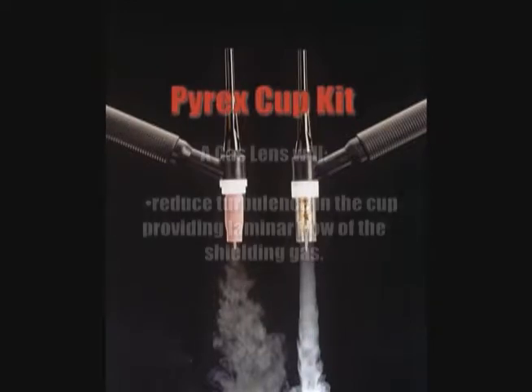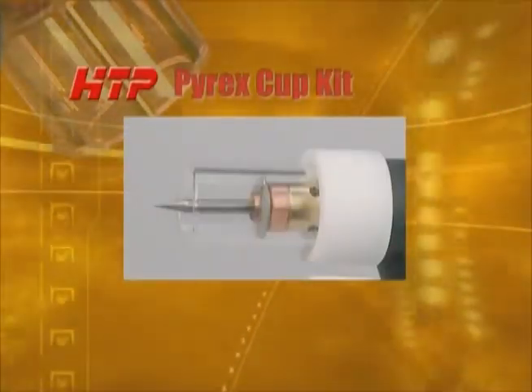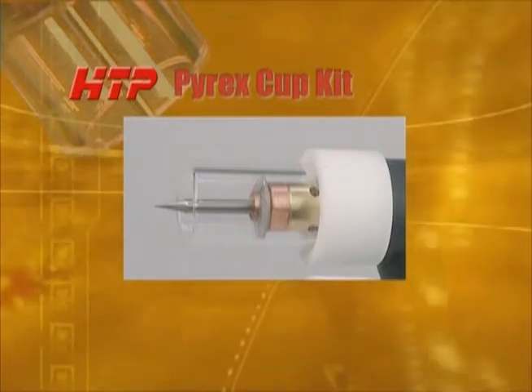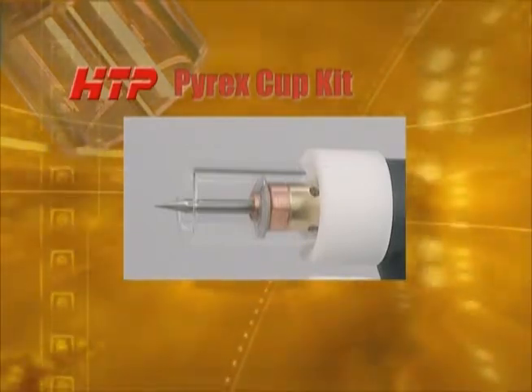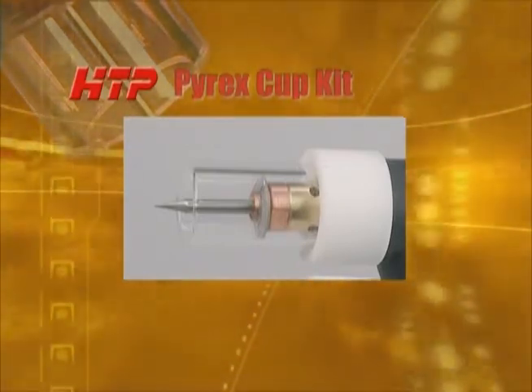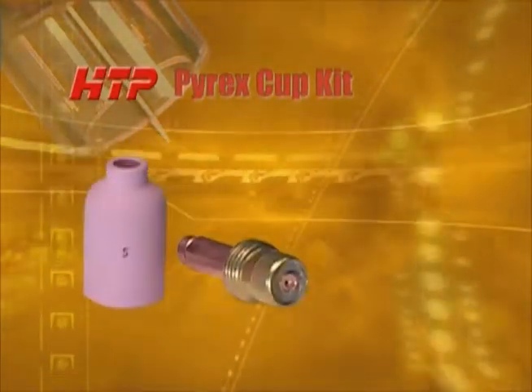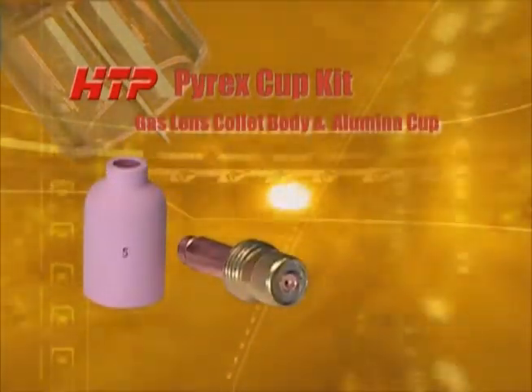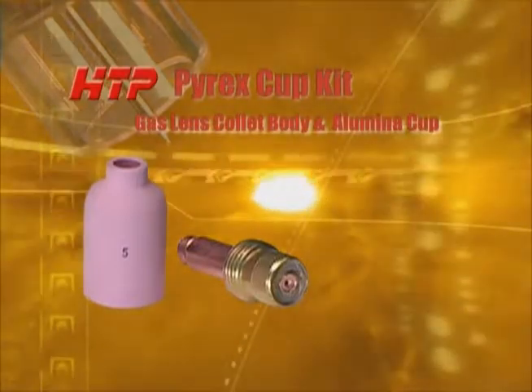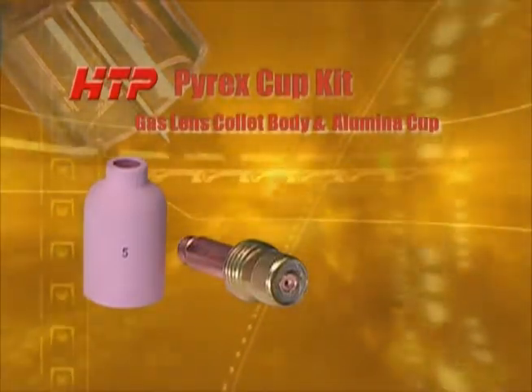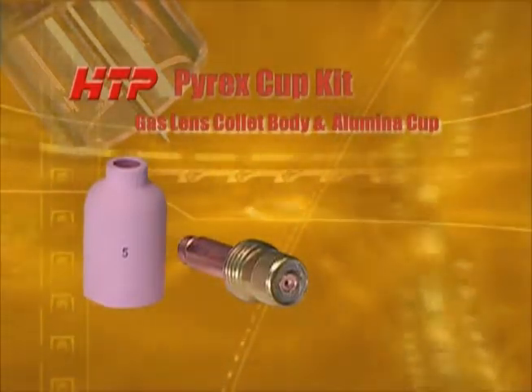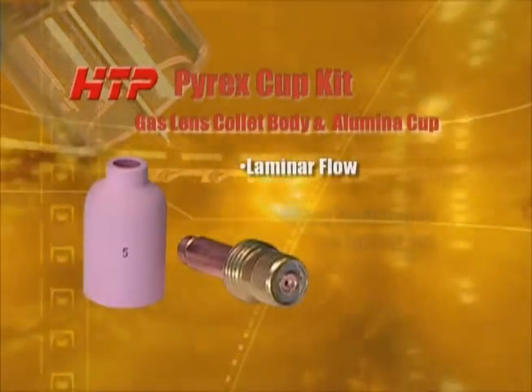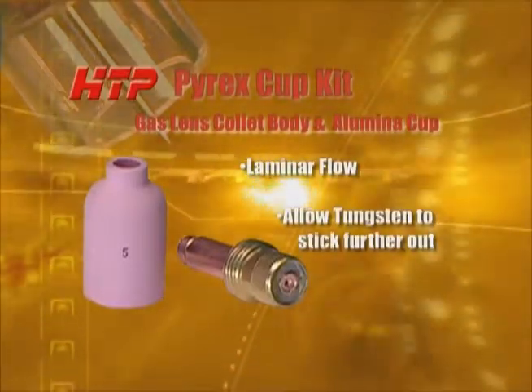Using the Pyrex cup kit in conjunction with increasing the shield gas flow rate will allow you to stick out the tungsten further to get into a tight spot. Here you can see a gas lens collet body and gas lens alumina cup. These replace the standard collet body and alumina cup. They give you the benefit of laminar flow and allow you to stick the tungsten further out, but the drawback is they are larger.